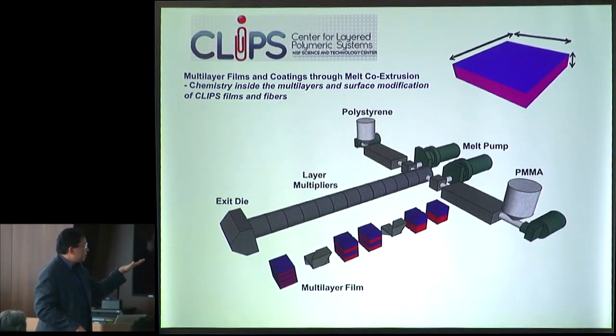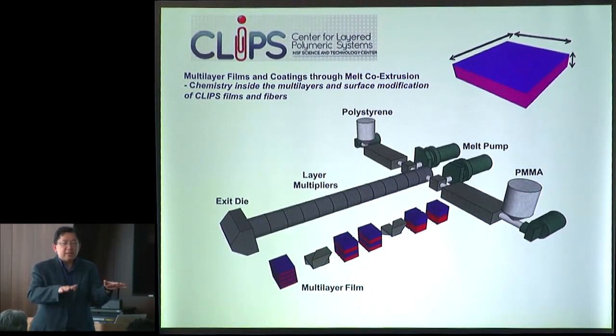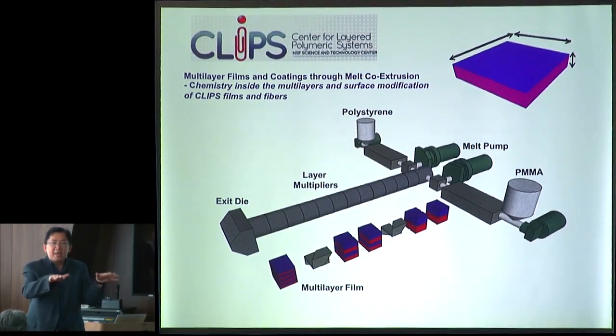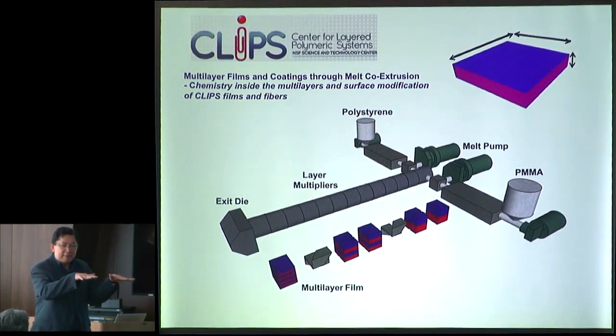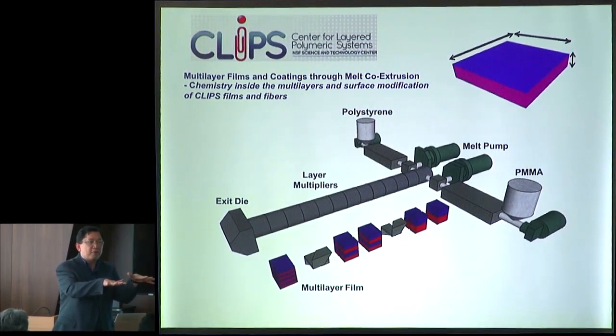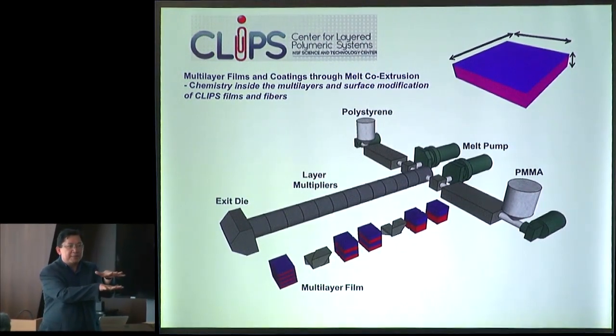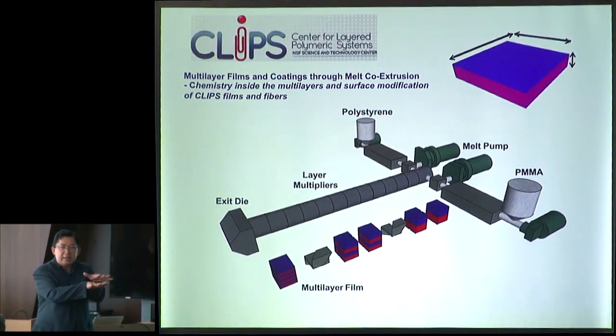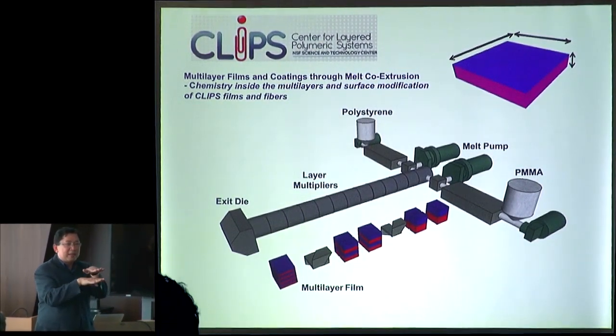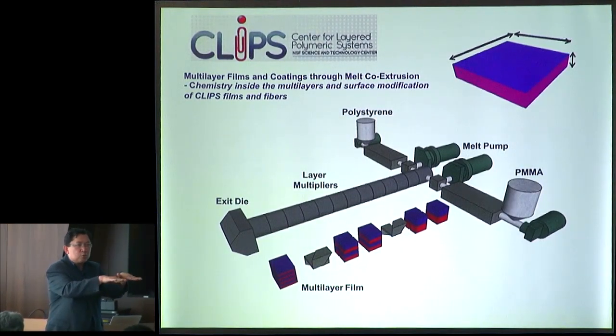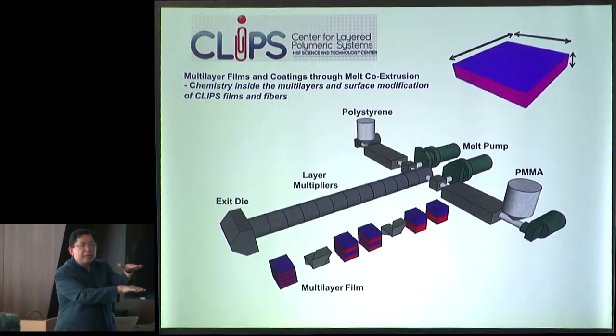So if I take polymer A, polystyrene, and polymer B, PMMA, and then I melt them. As they're melting, I'm pushing them, okay? And then as I push them, they form films. And as they form films, they lay on top of each other, okay? That bilayer is basically A and B polymer. Then I push them further, and I cut them in the middle. As I cut them in the middle, they separate into two tracks. And then I rejoin them by putting them on top of each other.